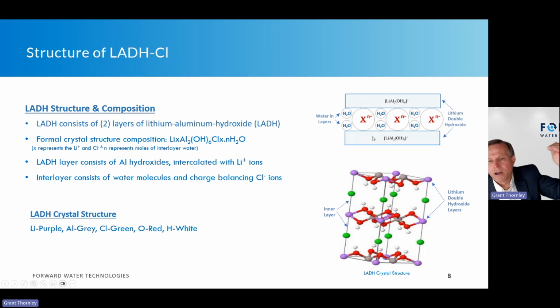If I bring one lithium cation in, I want to bring in one anion to neutralize those charges. So you always want a zero charge on the crystal structure. If there was a charge, you could have charge repulsion, and that would impede the media performance. So it's really important that if I'm bringing one lithium ion on, I'm bringing a chloride ion to charge balance that structure.